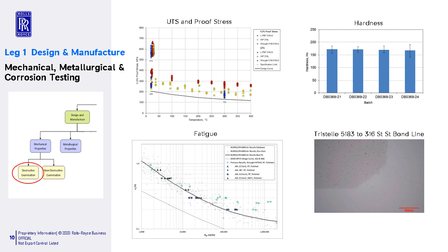So some of the key findings: the material has directionality and is anisotropic, as you would expect from a layer-on-layer build type process. All mechanical properties of the 316 material were equivalent to the wrought specification. However, we did see a slight increase in proof stress, which you can see on the slide in the top left figure, comparing the data in red against the data in yellow.